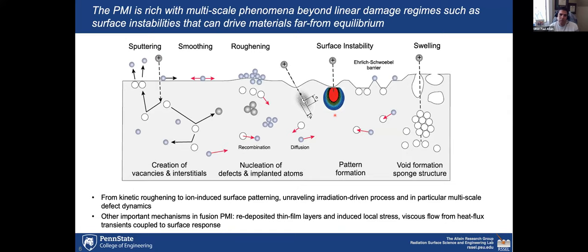We won't have time here. But the point is that when you think of energetic ions interacting with a material surface, we are going much beyond some of the more fundamental and basic concepts such as physical sputtering, which is the removal of atoms as an ion interacts with a material surface. There are ways for us to tune the parameters of these energetic particles so that defects can evolve on our surface, and we're able to then enable these atoms, for example, to self-organize on these surfaces, and not only approach what we call kinetic roughening, which is basically a random roughening of a surface, but we can direct these atoms to self-organize. And I'll show you an example of this.